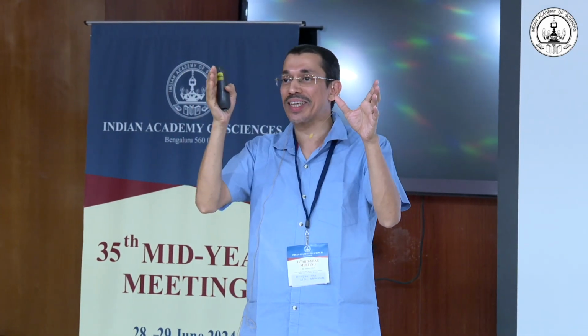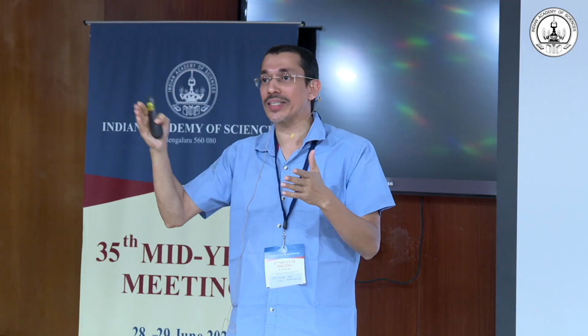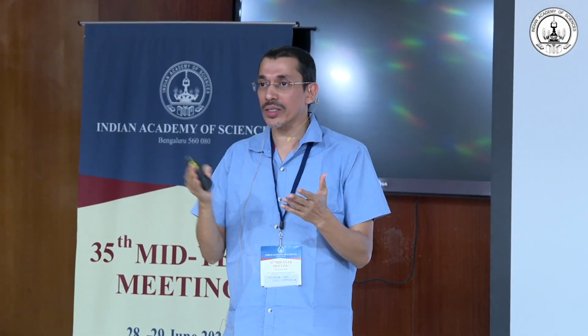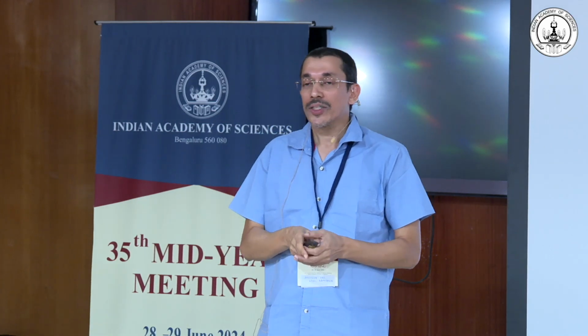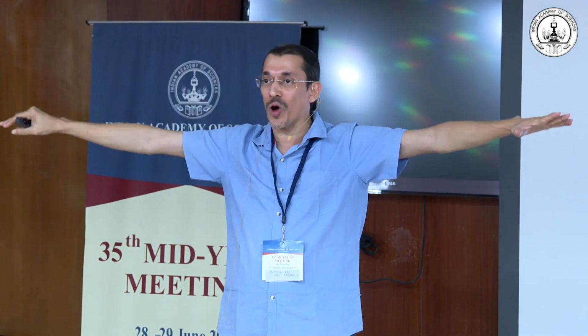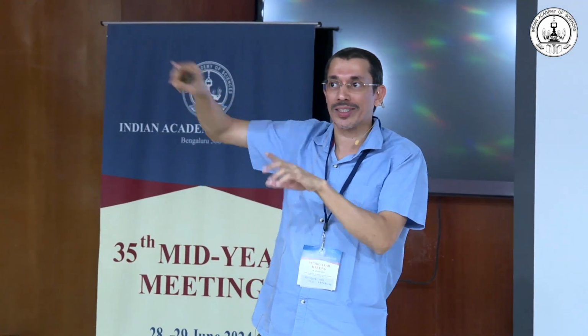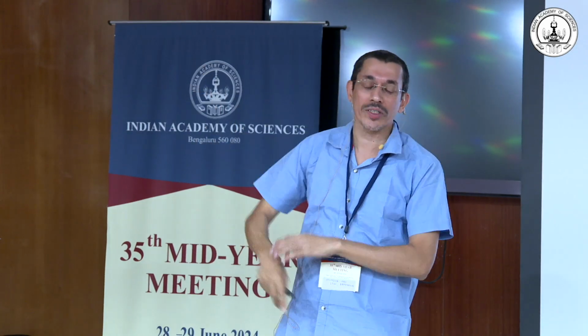In this experiment, accuracy depends on, so the only unknowns here are the resistance and temperature, because we know the Johnson thermometry is only 4 kB T R. The resistance is very accurately known, because we know the low frequency resistance very accurately. The only thing is that the noise you are measuring is this excess noise, because you are hitting on top of some background noise, and the background noise is determined not by the thermal background but rather by amplifier noise etc.